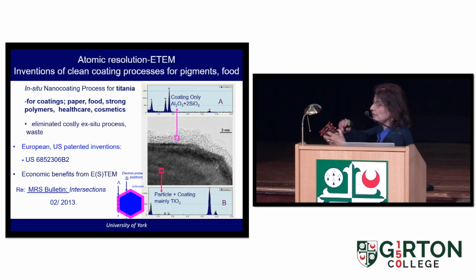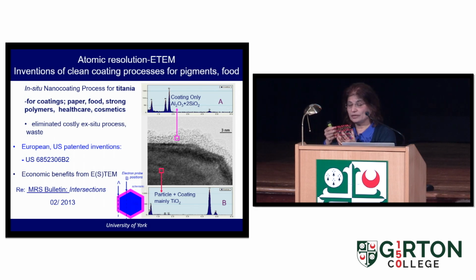So what they do is to coat it with ceramic coatings like alumina and silica, and it stops the sunlight getting to the TiO2. But what they were doing before was to use a wet process. Basically, they would dip a million ton of the TiO2 in hundreds of thousands of gallons of sodium silicate and sodium aluminate. It's a wet process and dry it out. And obviously, it's environmentally unsustainable and very expensive. So we said, can we come up with a dry process in our environmental microscope to put a nano coating without the wet process? And after one day, just one day of trying, we came up with this beautiful coating